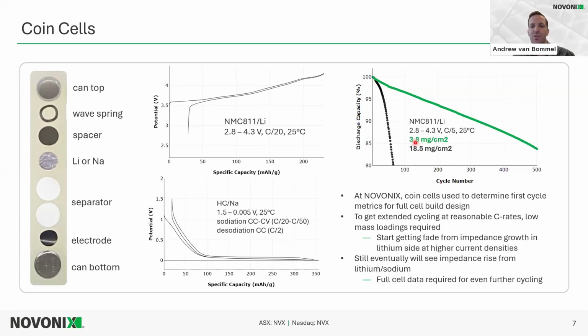So if we use a reasonable rate of C/5 for this cycling, we need 3.8 milligrams per centimeter squared, and we get reasonable cycling. So this is 500 cycles at C/5. We're still above 80% capacity retention. But eventually this will roll over because of that impedance from the lithium side. So full cell data is required for even further cycling. And just to let you know, this rollover seems to be even worse for us in the sodium case. So we have to be careful about what current densities we use, or we'll get that rapid fade.